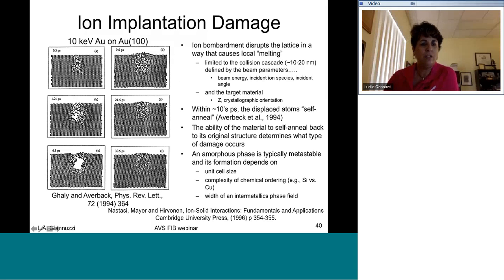So when all these atoms are jumbled up, like you saw in the video I showed earlier, this can be considered liquid-like in the sense that there is no structure here. There is no long-term order or any short-term order for that matter, okay? But what happens is that these atoms immediately start to relax. And whether or not, when they relax, they can find their equilibrium lattice positions will determine whether or not you form an amorphous layer or not, okay? So again, this all happens extremely quickly.